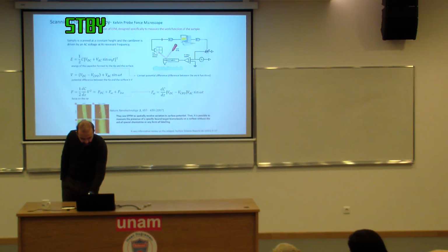And we observed that at grain boundaries, where we have crystals oriented in different directions, you get a very large drop in potential. That kind of thing is possible with these specific techniques.